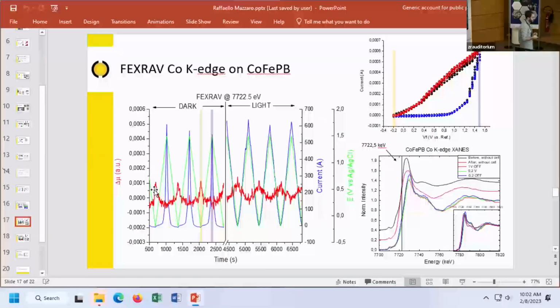And actually, this is a real signal, and we confirmed it by looking at the sample with a different acquisition method that is called FEXRAV. Basically, it's the acronym for Fixed Energy X-ray Absorption Voltammogram. So we keep a fixed energy for the X-ray. We chose the absorption edge, E0, the maximum derivative for the absorption edge, and then we sweep the potential in our sample, both in dark condition and illuminating the sample.